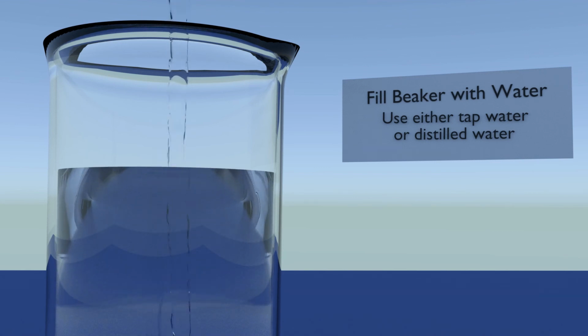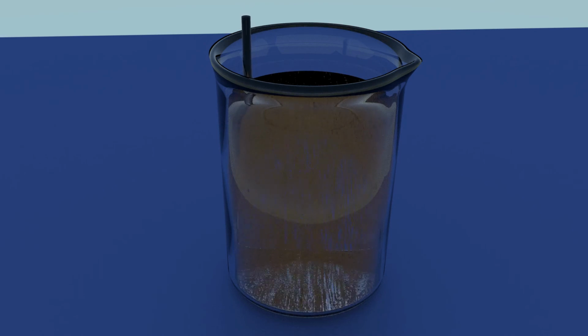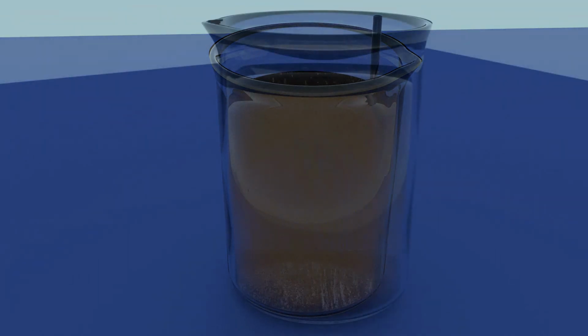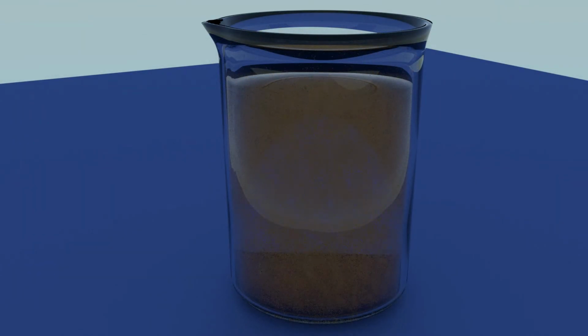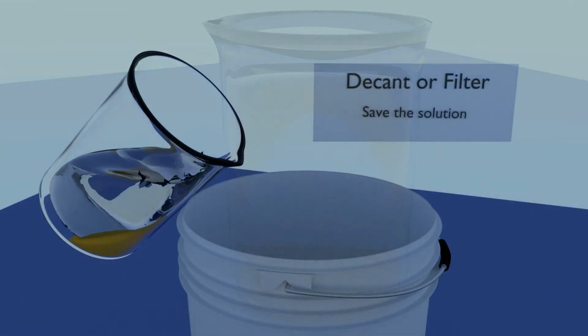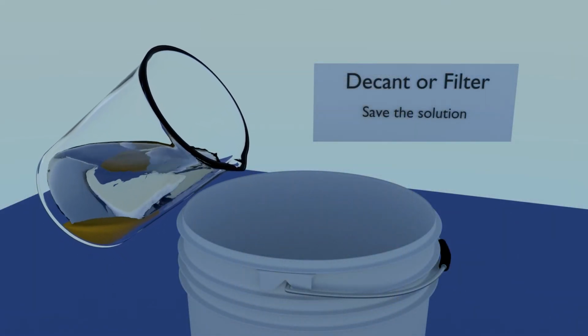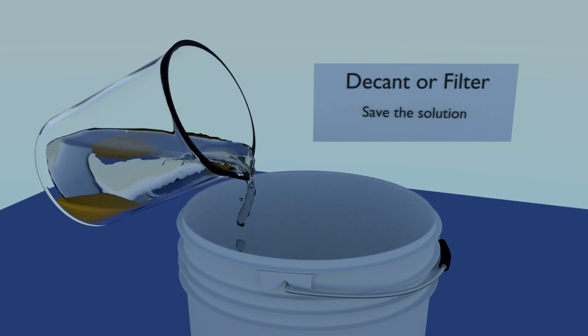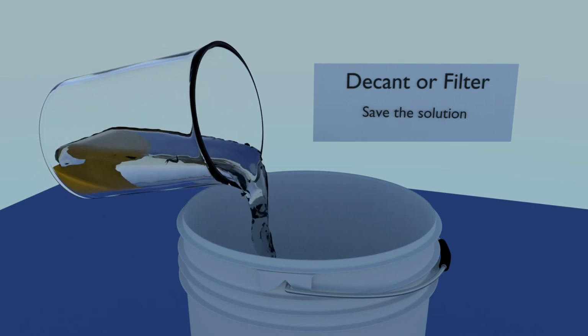Fill your beaker with water. Tap water is fine. Give the water a good stir, with a clean plastic or glass stirring rod. The gold particles will settle within a minute or 2. If sodium metabisulfite was employed, or the particles are tiny for some other reason, it may take a little longer. Once the particles have settled, decant or filter the water, and then rinse again with water.